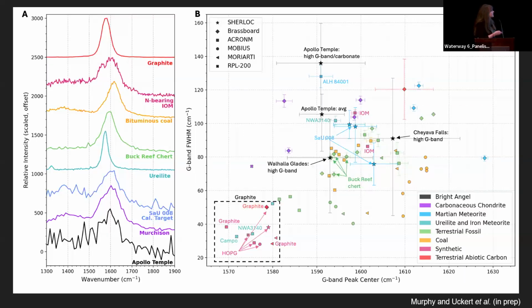So the next thing we did was compare the Bright Angel targets, the G band peak center and the bandwidth to reference samples that we had. So the shapes here, if it's a star, it's Sherlock. If it's any of these other shapes, it's a Sherlock analog where we collected reference data from. The colors here represent the different types of samples we used, and these error bars are errors on our peak fit uncertainty. So we use various meteorites such as carbonaceous chondrites, Martian meteorites, ureilite and iron meteorites,